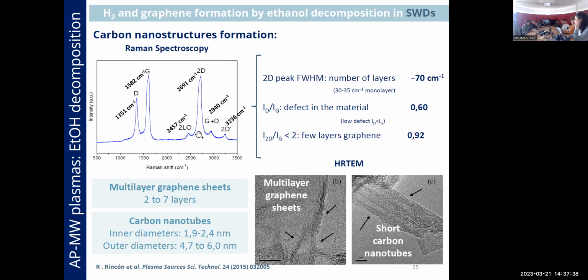The thinner this peak is, the better, because the full width at half maximum of this band is close to 30 to 35 in the case of monolayer graphene. So the closer to this value, the fewer graphene layers we will have.